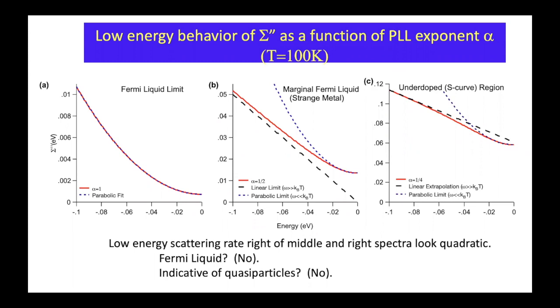Yeah, okay. So there's two things you need. Okay, so the question is about Kramers-Kronig, and what do you do because you need all frequencies? Yes. So first you need a cutoff at some deep energy, and we go quite deep. We go well past the bottom of the band, which is about half a volt. If we go to half a volt or a volt, there are very minor differences. And then there's the negative versus positive frequency side. And we're only probing the negative frequency, or the binding side.